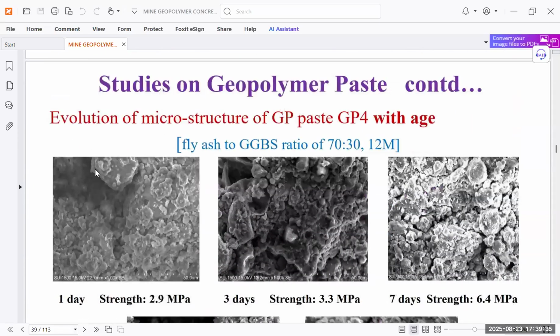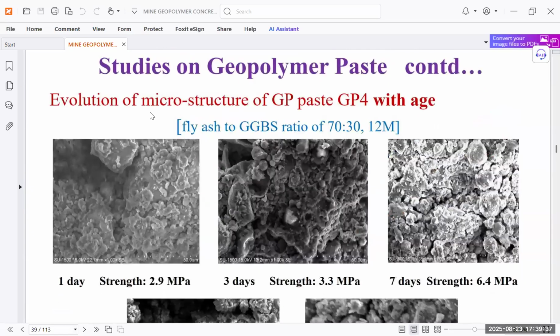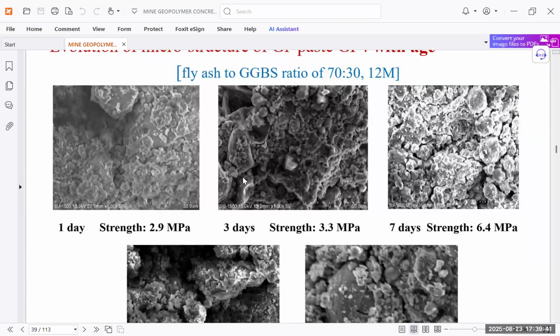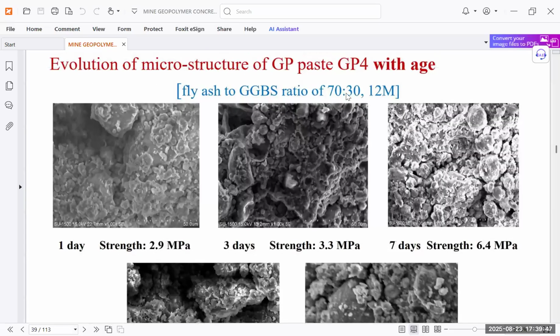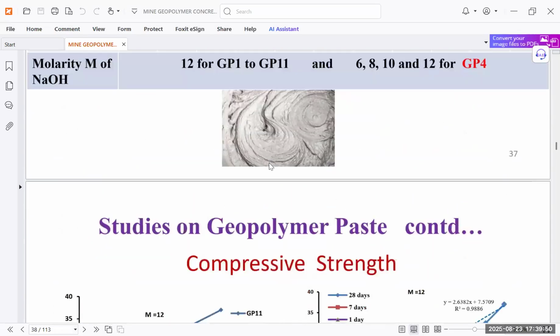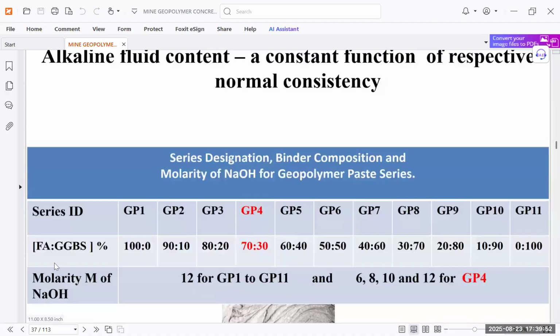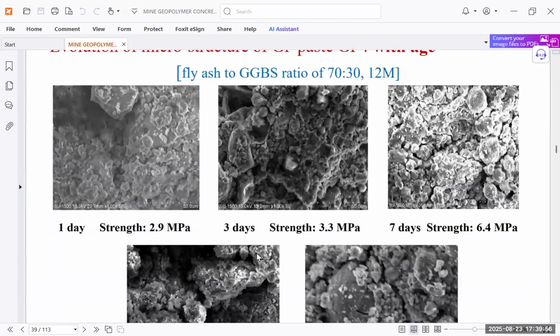Studies on geopolymer paste are also ongoing. The evolution of microstructure of GP paste and GP with age has been shown. You can see 1 day strength is 2.9 megapascal. As you can see, the ratio in this case is 70:30. This is for the GP4 part, in which fly ash to GGBS is 70:30. In this case, microstructure views we have shown.